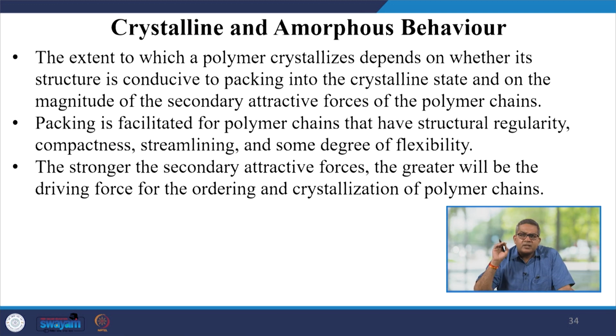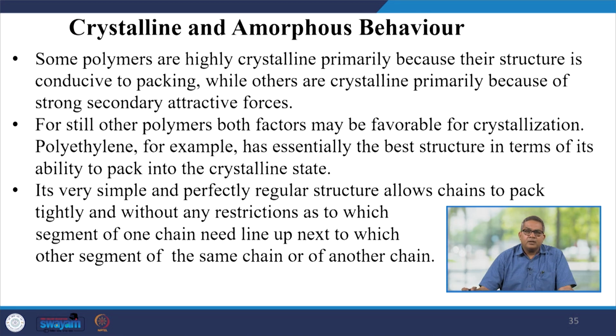Now, the extent to which a polymer crystallizes depends on whether its structure is conducive to packing into the crystalline state and on the magnitude of the secondary attractive forces of the polymer chains. Packing is facilitated for polymer chains that have structural regularity, compactness, streamlining and some degree of flexibility. The stronger the secondary attractive forces, the greater will be the driving force for the ordering and crystallization of polymer chains. Some polymers are highly crystalline primarily because their structure is conducive to packing, and in other polymers, both factors may be favorable for crystallization.